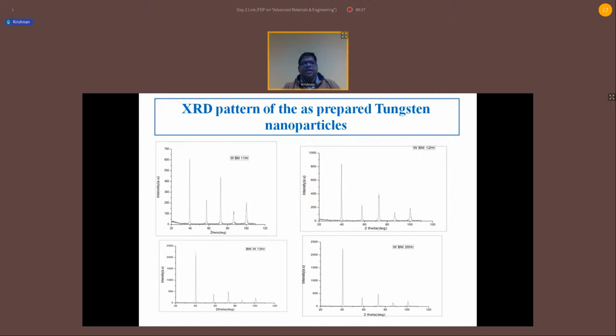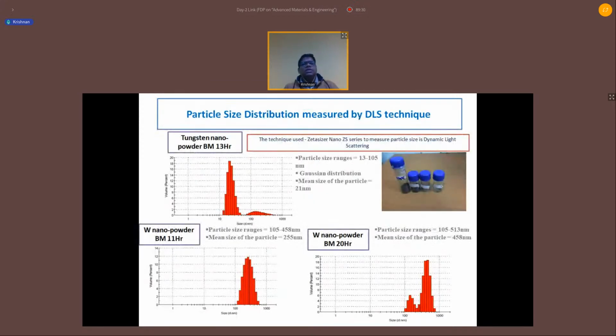We can also calculate the size distribution using DLS, the dynamic light scattering technique, which is also available in our department under Professor M.M. Ghosh. For tungsten nanopowder ball milled for 11 hours, 13 hours, and 20 hours, we got this size, but it is quite large. In 13 hours, the particle size range is quite feasible, and the mean size is 21. In the top right, the 4 vials contain the nanoparticles we have developed in our lab.